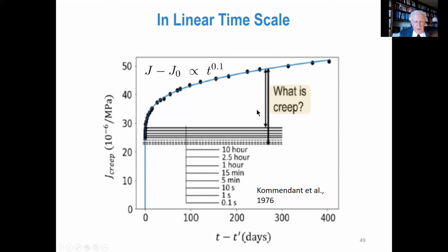So that gives a huge difference in the initial deformation, initial creep. And if people report creep rather than total compliance, which they often do, they report only this creep, not the rest. That error is carried all the way to infinity. It's a shift of the response curve.